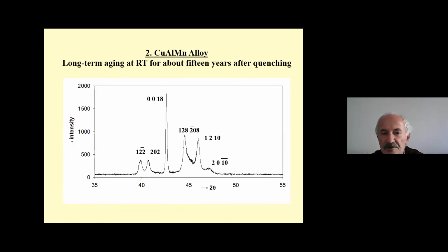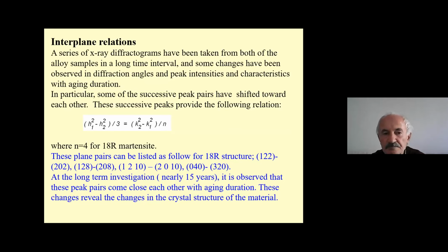This is another diffractogram taken from the second, copper-aluminum-manganese alloy sample after long-term aging at room temperature for about 15 years after quenching. As you can see, this diffractogram also exhibits the same character with these plane pairs. A series of X-ray diffractograms have been taken from both of the alloy samples over a long time interval, and some changes have been observed in the diffraction angles, peak intensities, and peak characteristics with aging. In particular, some of the successive peak pairs have shifted toward each other.